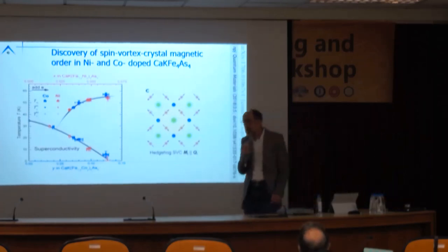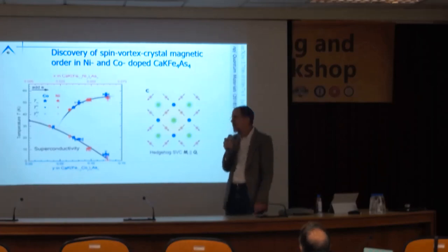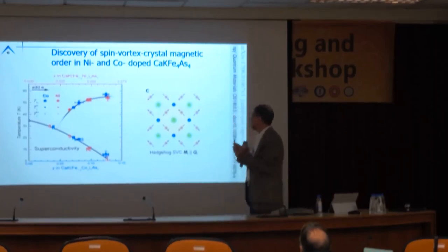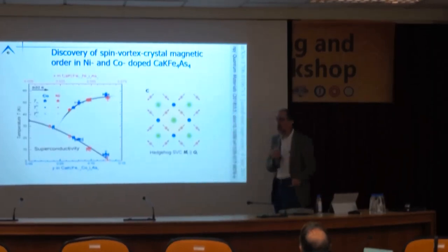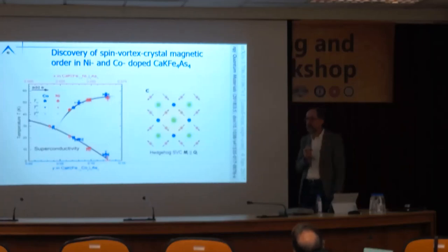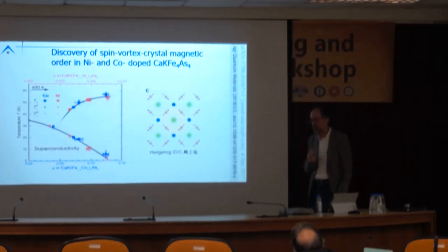So again on the 1144, is this magnetic structure different from what's claimed in the cesium and europium 1144, where they claim there's a ferromagnet and a superconductor? Let's be very careful. In those cases you have europium. It's divalent, but divalent europium has S equals 7/2, like gadolinium. That's what's going ferromagnetic. This doesn't happen here, so this is the bare transition metal magnetism. We don't have any rare earth having a separate magnetic transition. So no, that's quite different.